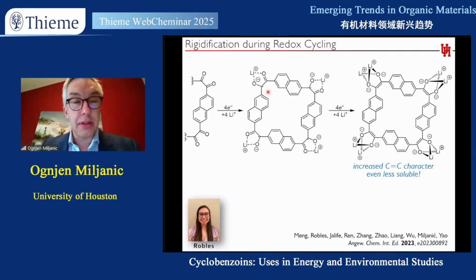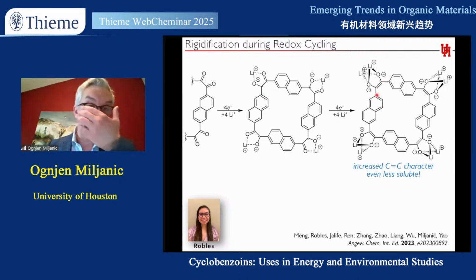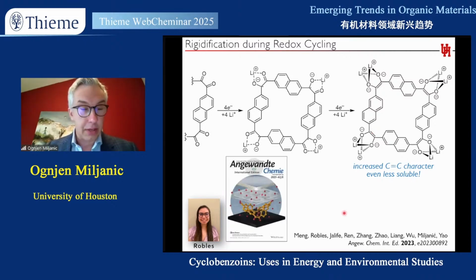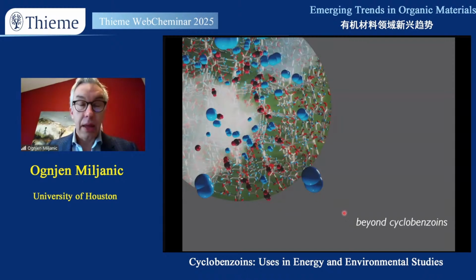These reduced radical anions are kind of difficult to probe experimentally, and so that's why we turn to computation. Our collaborator Judy Wu at the University of Houston has shown that indeed rigidification occurs during reduction, because as we place more electrons, the molecule becomes more rigid than the starting material, so the solubility doesn't increase. And this work was published a couple of years ago, and we were happy to get a feature on the cover. All right, well, this brings me more or less to the end of my talk.